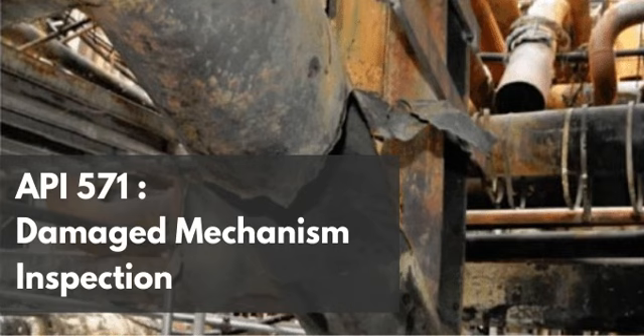Carbon steel, at ambient operational temperatures, typically features a body-centered cubic or BCC atomic lattice structure. Specifically, a ferritic or pearlitic microstructure, right? Correct. And this specific atomic arrangement, combined with its grain boundary chemistry, is highly vulnerable to the localized anodic dissolution caused by the amine. But when we upgrade to the 300 series stainless steels, the austenitic stainless steels, we're dealing with a completely different crystal lattice. Right, we move to the face-centered cubic or FCC structure. And why is FCC better here? The austenitic FCC lattice has more slip planes. It's inherently more ductile at a microscopic level, which allows it to distribute localized stresses much more effectively than the rigid BCC structure of carbon steel. Oh, that makes sense. It basically absorbs the stress better.